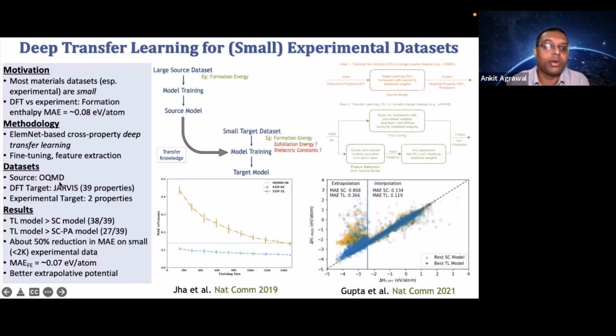We tried this cross property idea on 39 different properties from the JARVIS data sets, ranging from about 500 data points to 20,000 data points. And OQMD, of course, is more than 300,000 data points. When we did that, we found that the transfer learning models are already quite accurate, and we can get up to 50% reduction in error. On the cross property case, out of 39 properties, on 38 properties the transfer learning model was better.